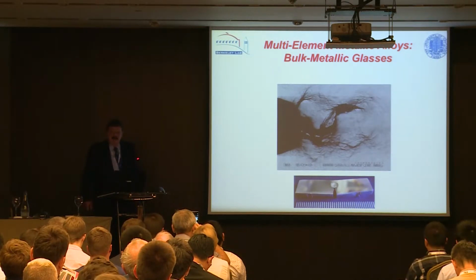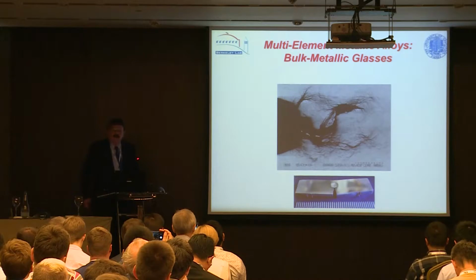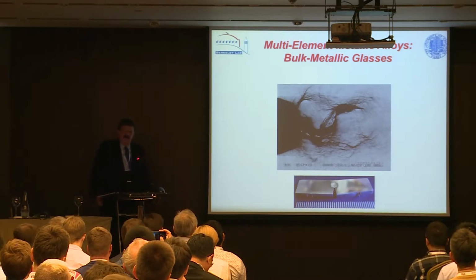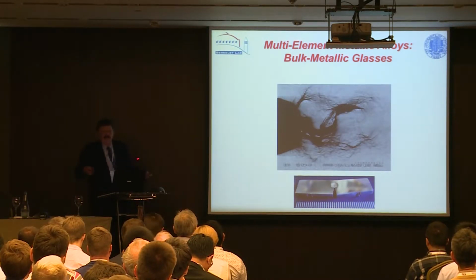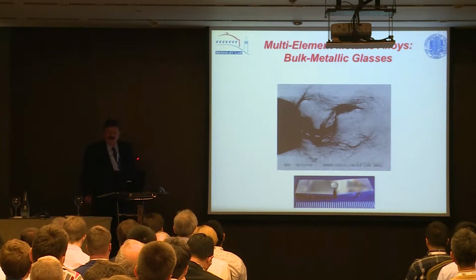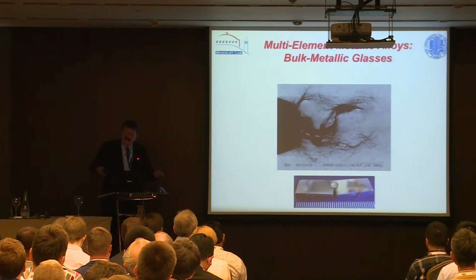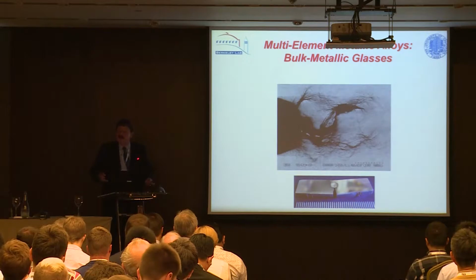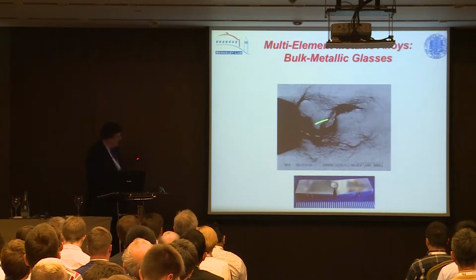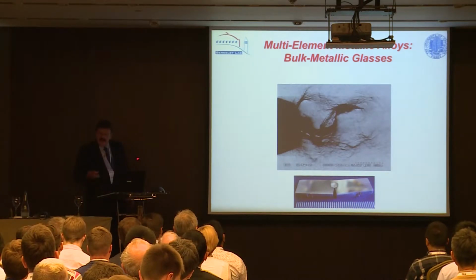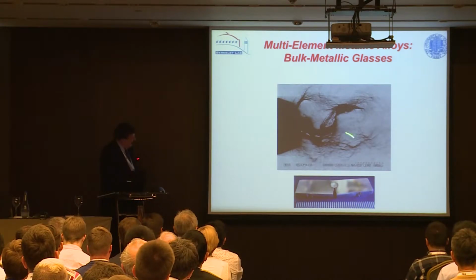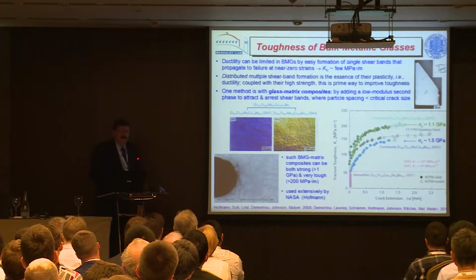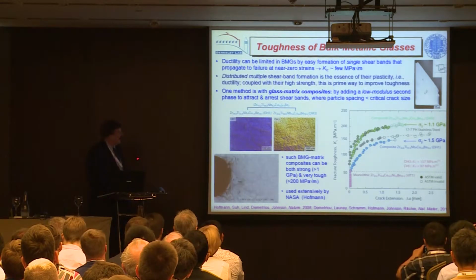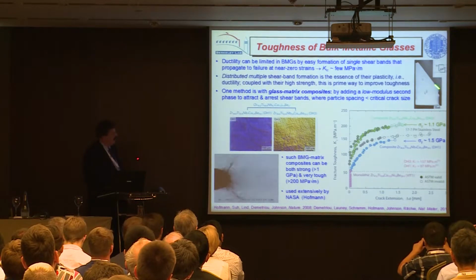These tend to have many elements in there, and the notion they form a glass is because of the so-called confusion principle. Each element has a different crystal structure, perhaps, and when they're all together, they get confused, and the kinetics are slow, and you can make a glass. Now, we think of glasses as being fairly brittle, but these are obviously anything but brittle. So these metallic glasses have a problem, in that they form shear bands,